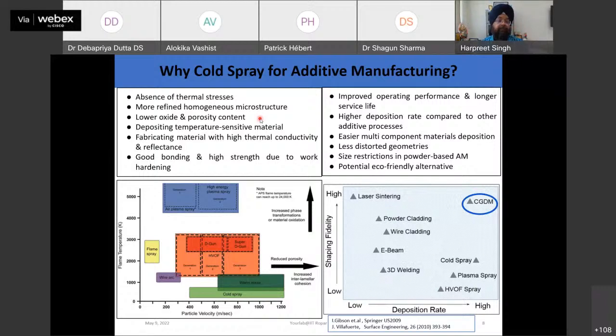So here, since temperature is very, very low in our process, there is no possibility of oxides. And of course, since you are consolidating the material very nicely on the substrate, your porosity levels are also very less. Another point is depositing temperature sensitive material, as I said, because we are not exposing them to very high temperatures, their metallurgy will remain intact.